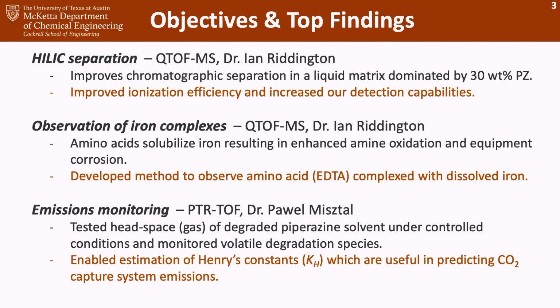Furthermore, with Dr. Ian Riddington, we were able to observe iron chelation using QTOF-MS. One of the degradation products we've begun to observe in our degraded piperazine solvent is amino acids. It's thought that amino acids are able to solubilize iron, and this is going to result in enhanced amine oxidation and equipment corrosion. So using QTOF-MS, we were able to develop a method that could observe these amino acids chelated or complexed with dissolved iron, and we did this using EDTA and iron as a base model.